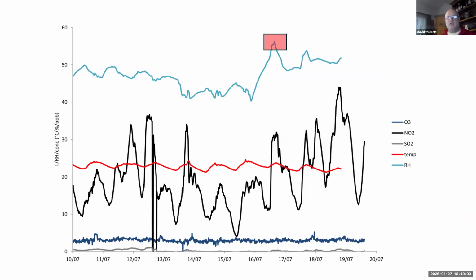Okay, so talking about metals and glass, they're both affected by relative humidity quite strongly, a little bit by temperature, but also quite strongly by pollutant gases. And this is a naturally ventilated building. The red is temperature, the pale blue is relative humidity, the black is nitrogen dioxide, and you can see both the temperature, relative humidity, but also the gas levels move up and down quite a bit.